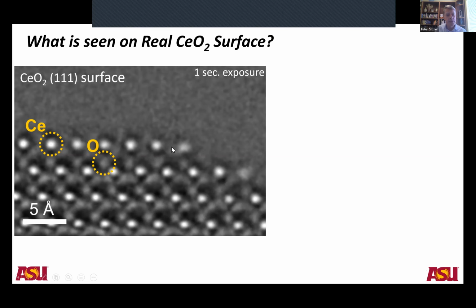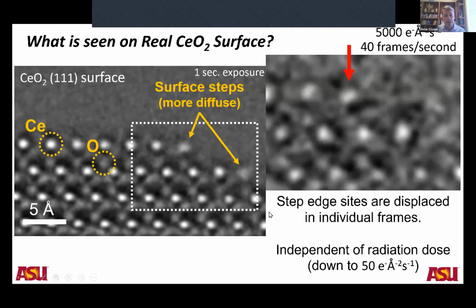What was interesting was that the defects, in this case the steps that we were interested in, always looked fuzzy. Again, electron microscopists have often seen this, where you'll say, well, it's jumping around, or it's out of focus. We've all seen it, and we just ignore it and look for a region of the sample that's stable. But with the direct electron detectors, this is a 1 second exposure. With the direct electron detectors, we can start to run the sensor at higher readout rates. This is 40 frames per second.